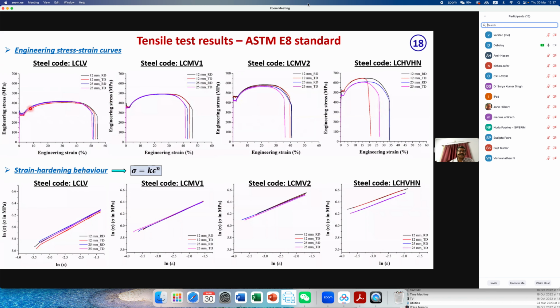Tensile properties. In the tensile curves also, RD and TD are not very different, so anisotropy is also not very high. These are 12 mm RD, 12 mm TD, 25 mm RD, 25 mm TD. In some of the grades, we have got a little bit of anisotropy in ductility that we have to study. But still, in high strength grades, our ductility is relatively very good. In general, we are getting more than 30% total elongation.